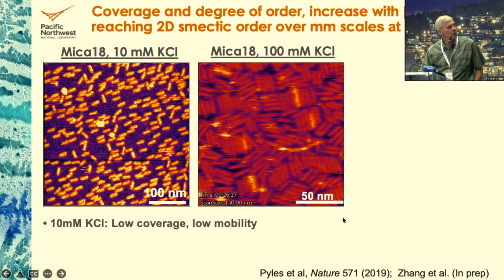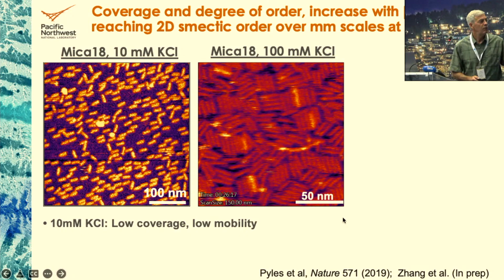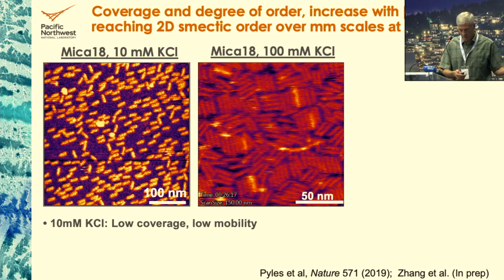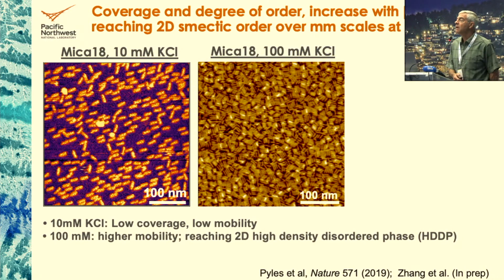And this takes a while to play because it's a lot of data, so I'll speed it up. And you can see what we end up with in this case. We end up with what's called a high-density disordered phase. That's the terminology for this in a threefold potential. This is just a larger scale image showing you what the end state is. Little domains that lie along one of the 3 directions.